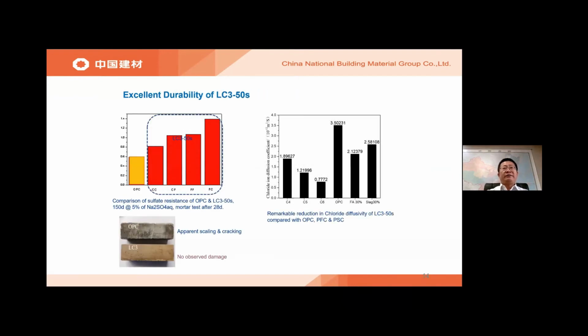There is very high resistance to sulfate corrosion for LC3 50 cement concrete, as well as very good resistance to chloride ingress into the cement or concrete. It's pretty much the same. We have done studies of this with the Indian partners. This is published. If you go on the web page, you can find that publication, in which they produced concrete of standard grades of 30 MPa and 50 MPa, and the amount of cement they had to use was pretty much the same as Portland cement. It could even have been a bit lower in some examples.